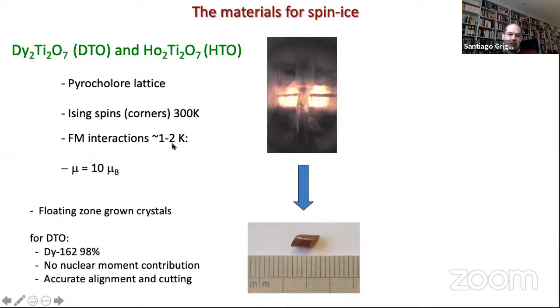You have ferromagnetic interactions between 1 and 2 K, and they have big magnetic moments of the order of 10 Bohr magnetons. So we grew some crystals using the floating zone. The dysprosium titanate is from our lab, and the holmium titanate comes from Prabhakaran in Oxford. And for the dysprosium titanate, we used not naturally abundant dysprosium, but an isotope of dysprosium, for two reasons. One is that naturally abundant dysprosium absorbs neutrons a lot, so it's impossible to do neutron experiments with that. And the other is that this isotope we use has no nuclear moment. So essentially, we wanted a system as pure as possible.